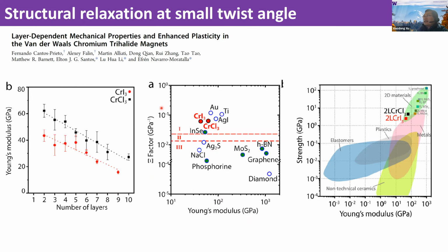And here I also show data extracted from this paper. They measured the elastic properties of these 2D magnets. In the middle, they show these deformation factors. You can see that chromium triiodide, for example, is here. It's easy to deform. But for graphene and MoS2 at the bottom right corner, it's hard to deform. They also show the Young's modulus and the strength. Strength means how large a strain you need to apply to break the samples. You can see that BN and graphene are here on top. They're really stiff and really robust materials. But chromium triiodide is still better than plastic, though not as stiff and as strong compared to graphene or MoS2. So because the material is much softer, when we stack at small twist angles, the lattice tends to reconstruct. That's the main reason we don't see the Moirés.